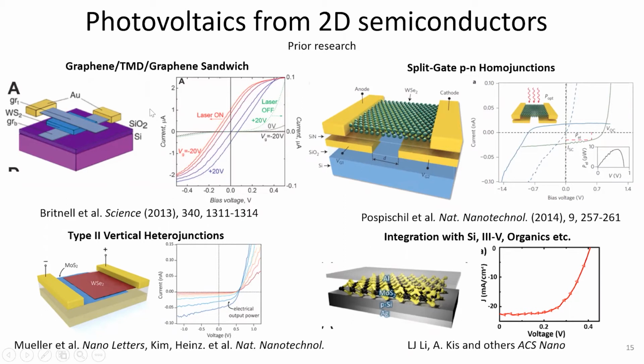Of course, there was this early work again in 2013 about sandwiching a TMD, say WS2 or WSe2, between two sheets of graphene, and one graphene was more highly doped than the other. So this was again, in some sense, an asymmetric PN junction, which was showing photovoltaic effect. As I mentioned on the previous slide, people have also used split gates, and by using a split gate on an intrinsic semiconductor, you can induce one side to be P and the other side to be N, depending on the gate bias you apply on either of the split gates, and then you can generate a photovoltaic effect.